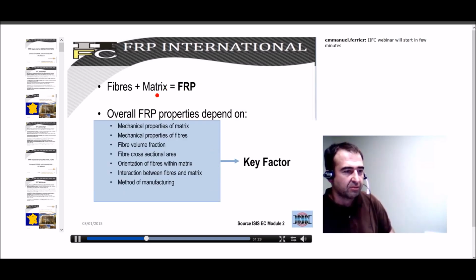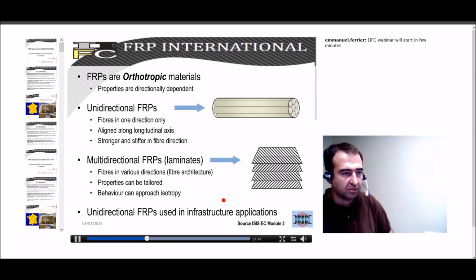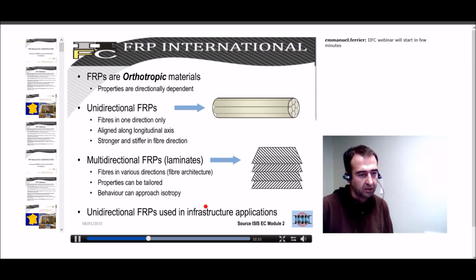So FRP is a mix of fibers and matrix, and the mechanical properties of FRP will depend on the matrix, as I mentioned, on the fibers, but also on the amount of fibers in your mix and the adhesion. If we look at the mechanical properties, you have to understand that the mechanical properties of UD fibers are given, and you can have very good properties of fibers. Then you have two things to understand: the fibers are bound together, so there will be the problem of physical and chemical properties of the surface and the interface between the fibers and the polymer. And then you have the laminate, so it means that you will have a lot of layers, and all those layers have to bond together perfectly.